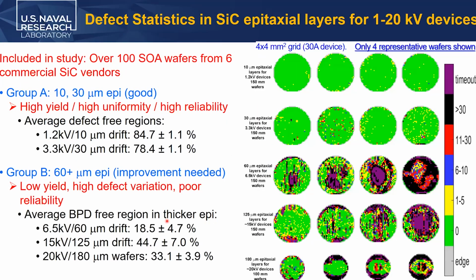So just very quickly, this is a survey of more than 100 wafers. This is the state of the art wafers. We just did it over the last couple of years. And as you know, silicon carbide is the only mature technology which has devices available up to 15 kilovolt range in the market. So we have done a study on these from 1 kilovolt all the way to 20 kilovolt, and we see a large variation.